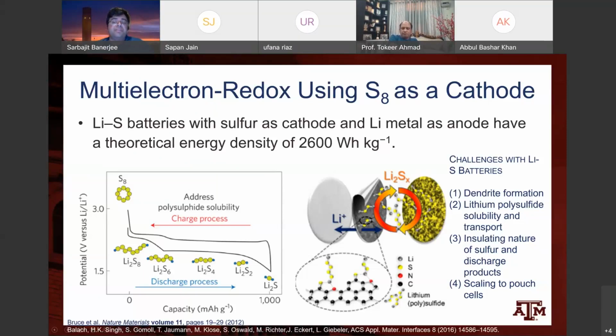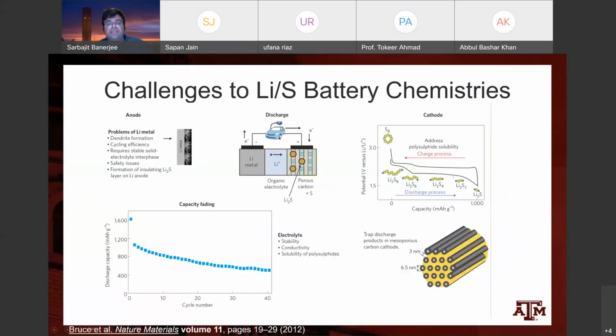And then the other challenge is that, again, because of the insulating nature of sulfur and discharged products, you end up not being able to use just sulfur. You end up losing a lot of capacity because you're using sulfur loaded onto some sort of a host lattice. And really, there was a lot of promise in the last decade as people started exploring this chemistry. Some of this promise has turned to disappointment because there are some real big challenges in scaling these into pouch cell levels. So this has been a huge problem.